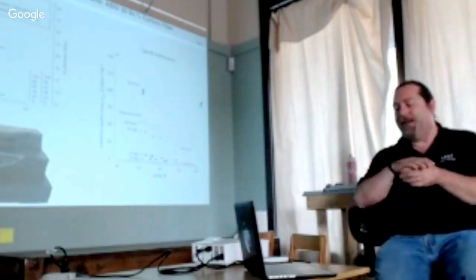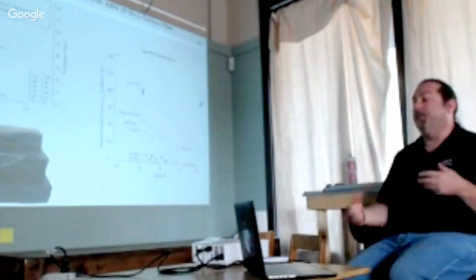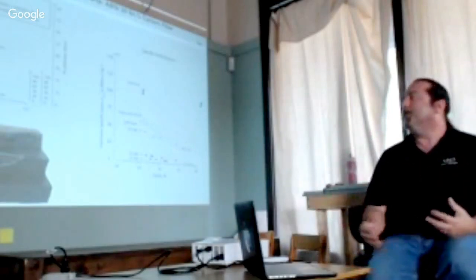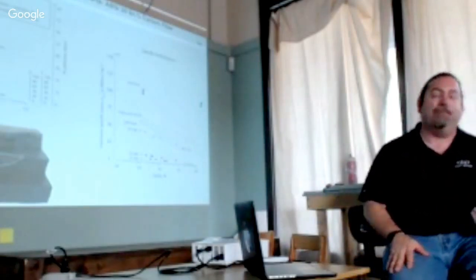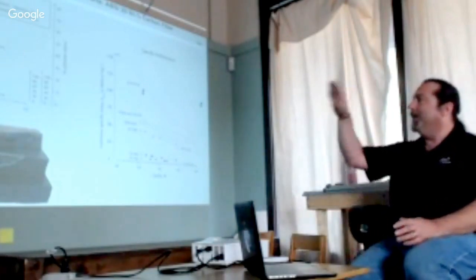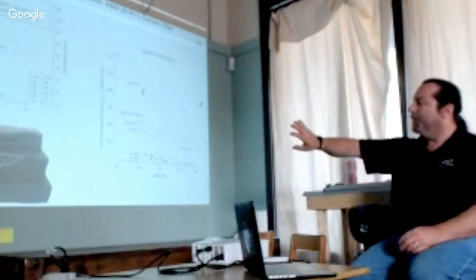But when I first came in and I saw this structure, it has a lot of defects between the layers, I was very concerned about the fatigue performance. So one of the first things, beyond just this quasi-static tension type test, we did the fatigue testing. And so this just shows that data in X, Y, and Z direction. It shows the fracture type surfaces you get in fatigue.